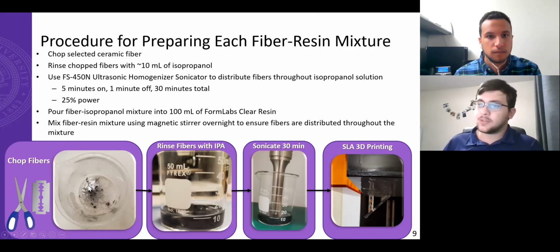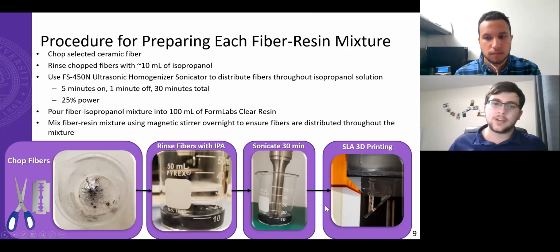So we chop the fibers with scissors, then rinse the fibers using isopropanol, roughly 10 milliliters, before putting it in a sonicator for 30 minutes, 5 minutes on, 1 minute off, at 25% power of our ultrasonicator. And it's a horn sonicator. That's just to distribute the fibers throughout this mixture before we pour that into the resin, and then we'll use that resin to do our SLA 3D printing. But we'll mix it into the resin overnight using a magnetic stir at a little over 125 RPM.